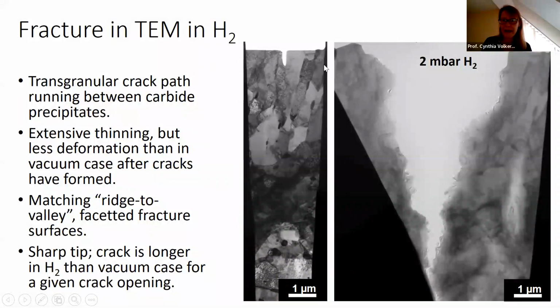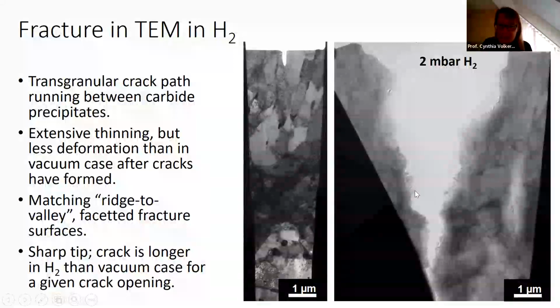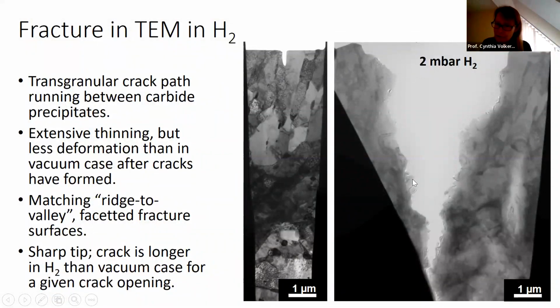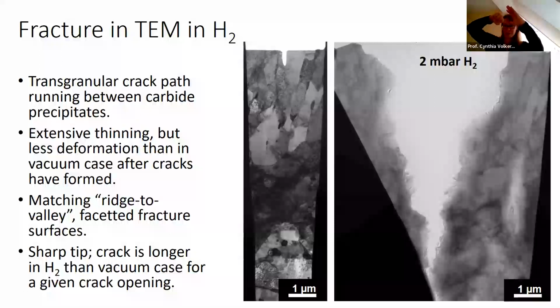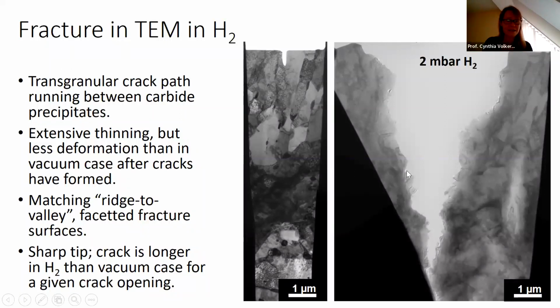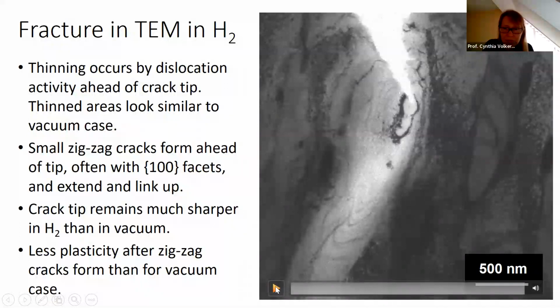Here is once again beforehand and afterwards, and maybe you notice already that this is quite a different crack feature. First of all, we have a sharp crack that even the tip runs off the bottom of the page here. It's also transgranular and moves between carbide precipitates, and there's also extensive thinning. But the crack tends to be a little bit flatter, and instead of ridge to ridge as we had before, we have here ridge to valley. So they are matching interfaces. This is an indication of very different processes that go on during crack propagation. Let me show you the video so that you can see how different that is.